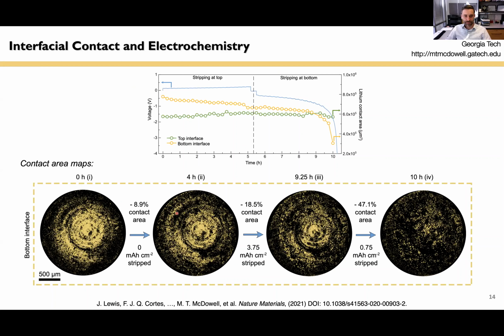This set of images below now shows what we call contact area maps. So now we're basically looking through the interface and we're projecting all the pixels of contact. So the yellow pixels are pixels where there is contact between the solid electrolyte and the lithium. And at the beginning, it looks like this. This corresponds to a high overall area of contact shown up in the plot above. And then as we cycle, we lose some contact area, but really in the last 45 minutes of the experiment, we lose half of our contact area.